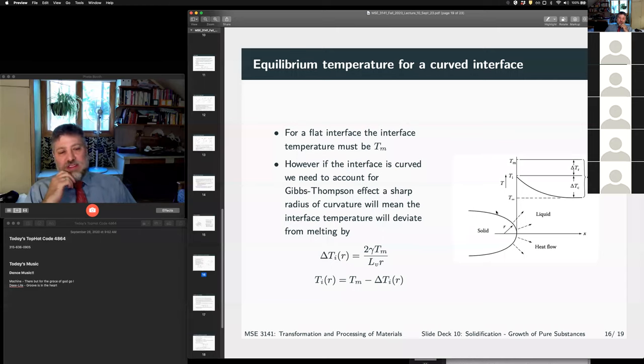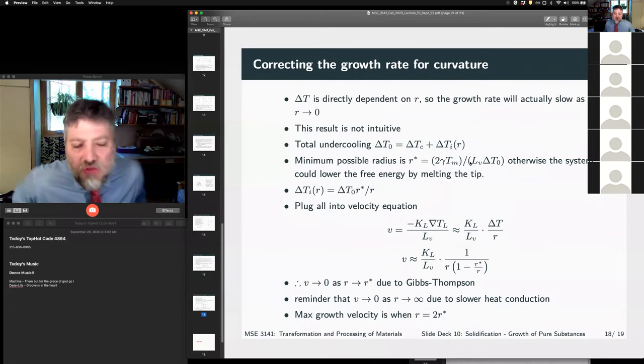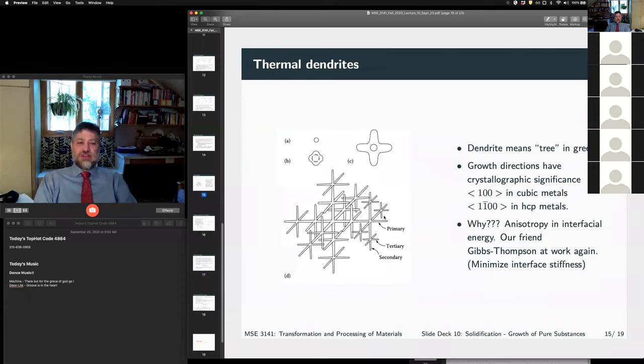So what does this tell you? The tip, the size of your dendrite arm here, is going to be strongly related to the undercooling, because R star is a function of the undercooling, right? So homogeneous nucleation can give you the smallest dendrites simply because R star is very small, right? Okay, so that's growth of pure metals. These thermal dendrites here that we see, right? These are very, very rare to encounter, right?